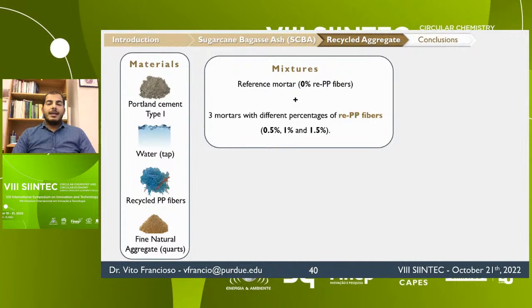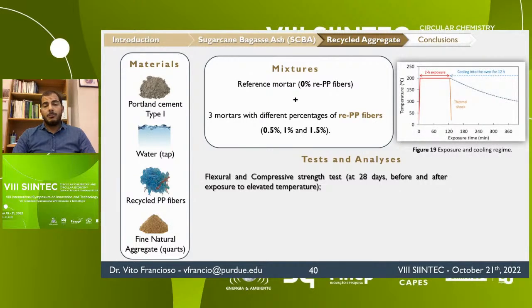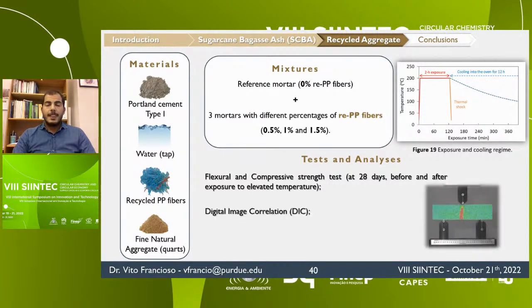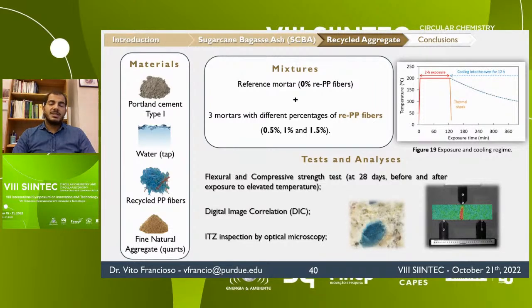For this study, I designed 4 mixtures: a reference one without any fibers, and 3 mortars with different percentages of recycled polypropylene fibers: 0.5%, 1%, and 1.5%. The flexural and compressive strength tests were performed at 28 days before and after exposure to elevated temperatures. Besides, the digital image correlation (DIC) technique was adopted to study the evolution of crack propagation and strain distribution in the specimen during the 3-point bending test. And finally, the interfacial transition zone was inspected by means of a digital optical microscope.